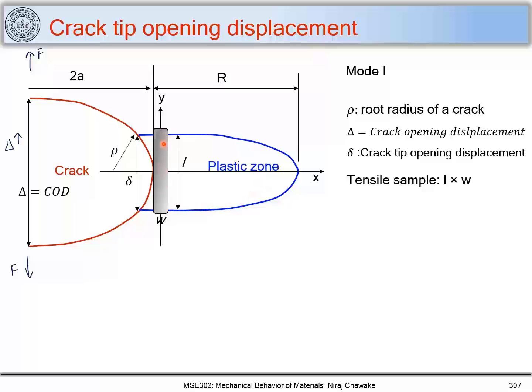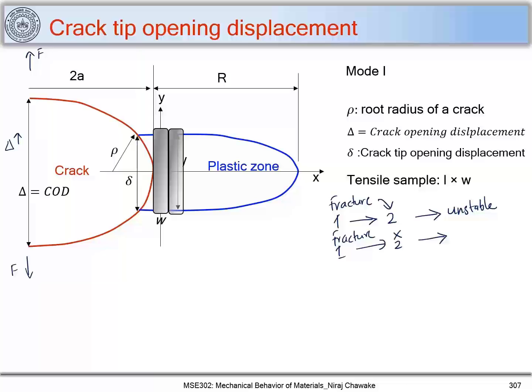Now, when this sample breaks, it passes a strain on to the next sample like this. So here you can consider another sample, and when this sample breaks and it causes a fracture in the next sample, in such a case we call this crack unstable. When this sample fractures but it doesn't cause any fracture in the second sample, such a case is called stable crack growth. So let me write that down. So you have these samples. When sample 1 causes fracture in sample 2, this is called unstable crack growth. So when sample 1 fractures but doesn't cause any fracture in sample 2, this is called stable